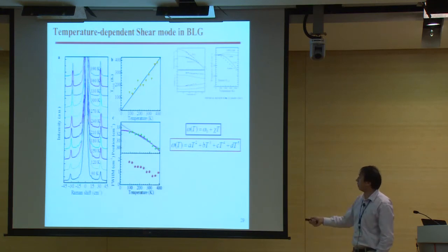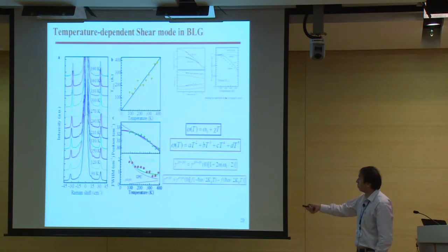And similarly, we can fit the width of the shear mode as a function of the temperature, and we can plot the overall total effect of phonon-phonon interaction and electron-phonon coupling contribution. And when we plot them separately, we can tell that for this shear mode, the EPC is dominant.